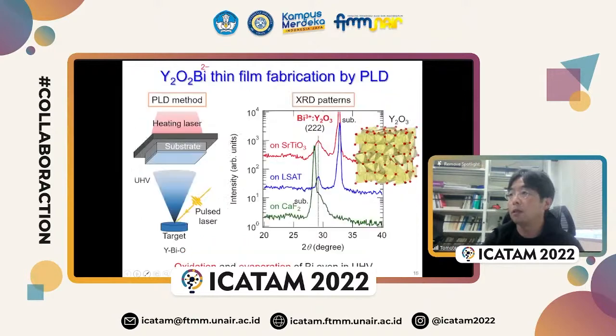So next we tried to make an epitaxial thin film of this compound by using pulsed laser deposition. In pulsed laser deposition, we have some starting materials, and by irradiating a pulsed laser, we can evaporate these starting materials, and finally we obtain the epitaxial thin film.